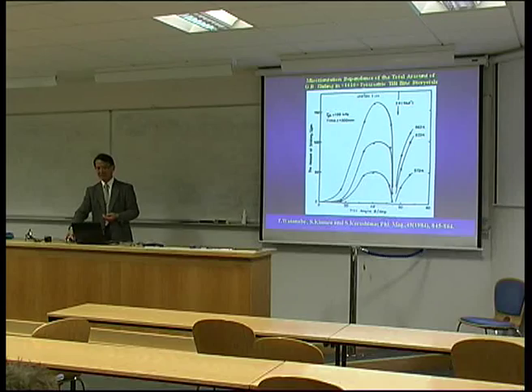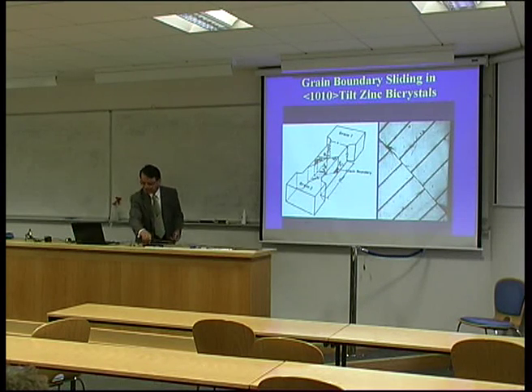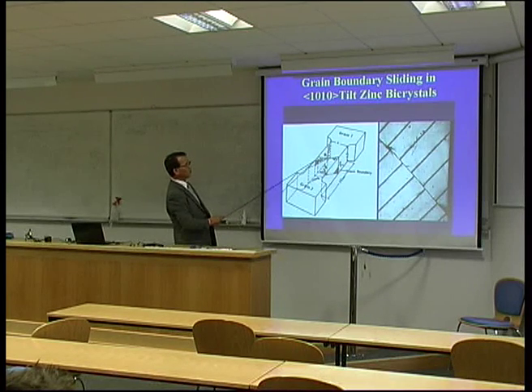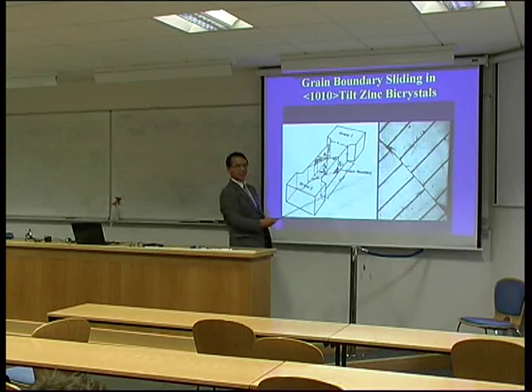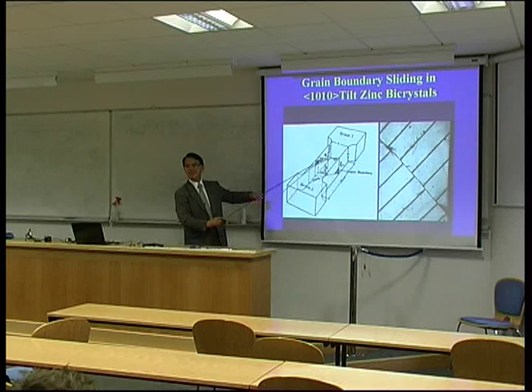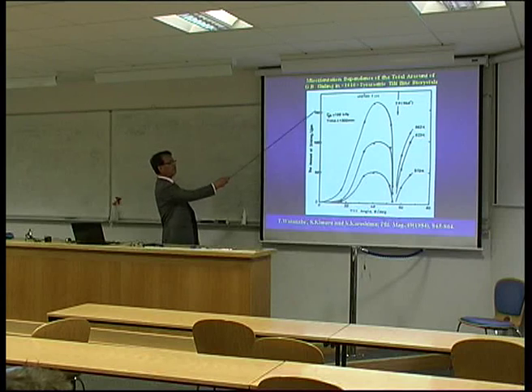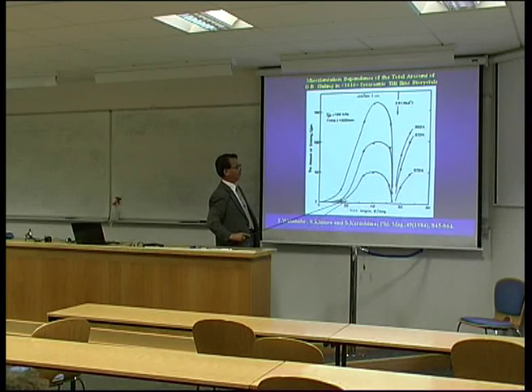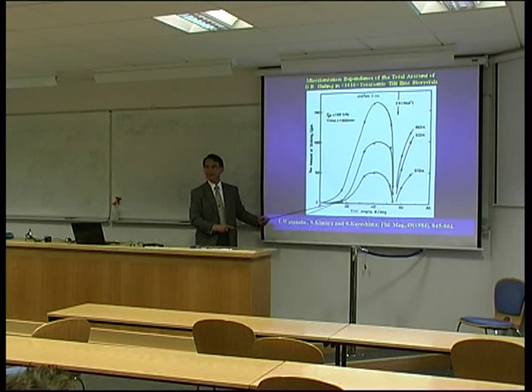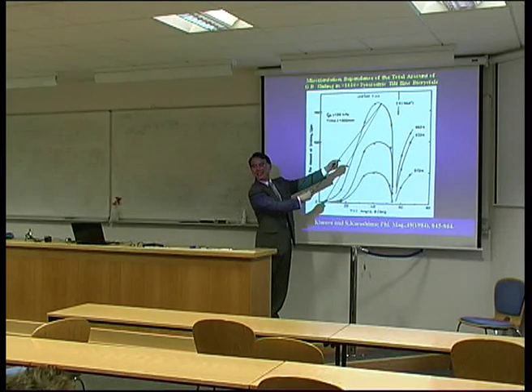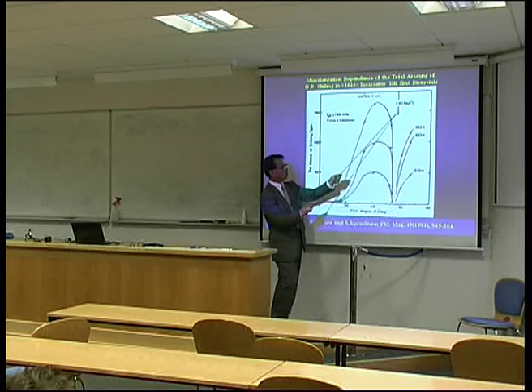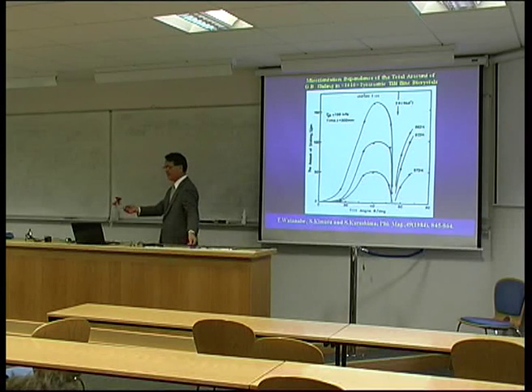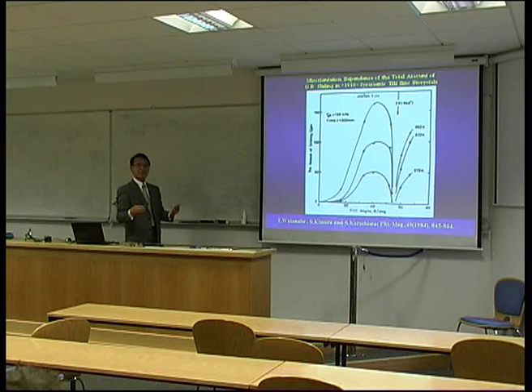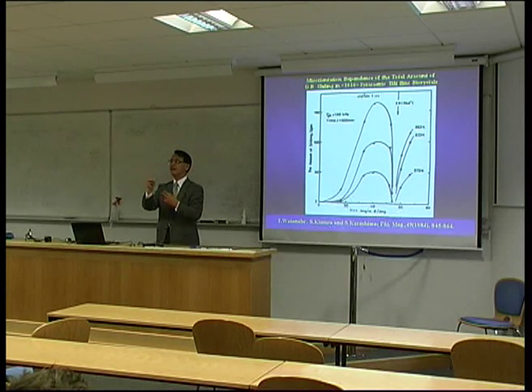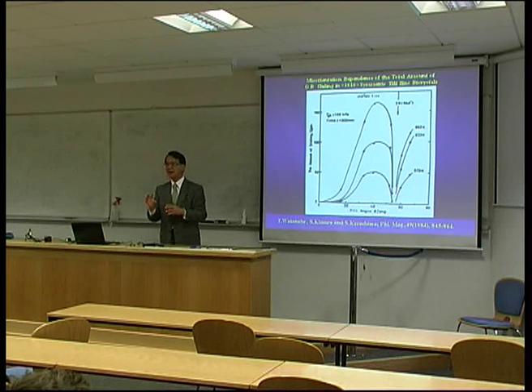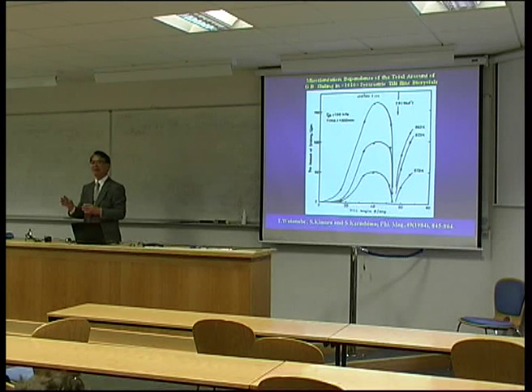And even for grain boundary sliding, another 1 minute, sorry. If you use a bicrystal sample and put a scratch across the boundary, you can measure the sliding direction, and if you change the misorientation systematically, you can determine how the boundary sliding behavior changes depending on misorientation. So low angle boundaries are very difficult to slide, but with increasing misorientation, boundary sliding becomes easy. But even at higher angle, a coincident boundary cannot slide. So depending on the boundary type, this produces heterogeneity in grain boundary behavior in polycrystals. So you have to consider such differences, the different roles of grain boundaries in real polycrystals.